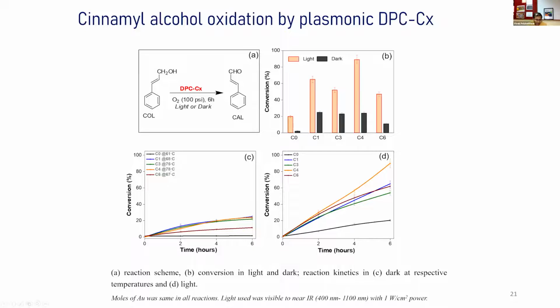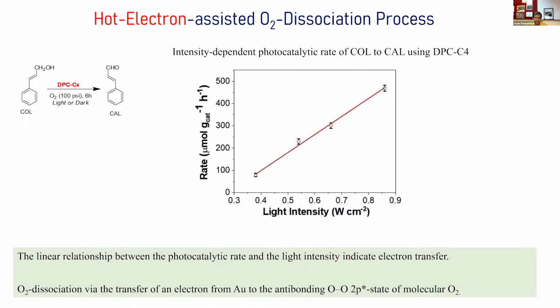But then we measured the temperature the reaction mixture reached when it was exposed to light and heated by the light, and then we carried out the reaction in the dark at that temperature so that you normalize the impact of the temperature. So this data is in both cases at the same temperature, clearly indicating that it is not the temperature but something else that is the cause of the better activity when I use light. So what could be that cause? What could be the reason for better activity? The hypothesis was that when I expose the catalyst to light, you produce these hot electrons.